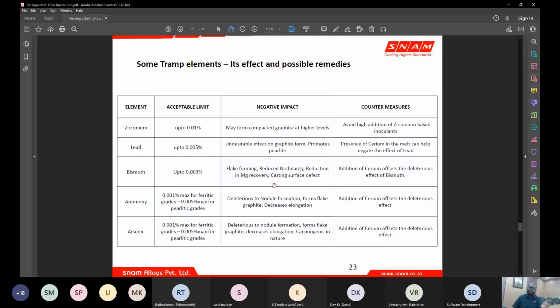Lead again leads to scattering or degenerating your graphite forms. It promotes pearlite to some extent, but before promoting pearlite, lead will distort your graphite. And if it is a thick section, it is much more dangerous because the cooling rate is very slow. When your cooling rate is very slow, by default your nodule forming capacity is reduced, and holding the carbon in spheroid form becomes very difficult in a thick section casting. That is why your nodularity is always slightly poorer in thick sections than thin sections.